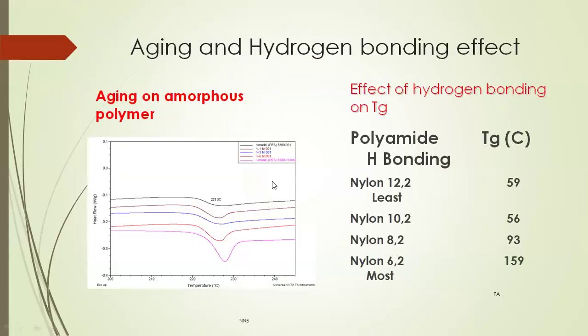We will see these factors one by one. I told you that aging affects the TG. Suppose many times we deal with amorphous polymers, and when the material comes, you immediately do one experiment, many experiments. Then you keep your amorphous polymers on a shelf, and after 3 or 4 months, you again take the same sample and repeat your experiment, and you don't get similar results. Why? Because your amorphous polymer ages with time. So how to find out whether your material is aged? Because each material has a shelf life. After that, it starts aging.